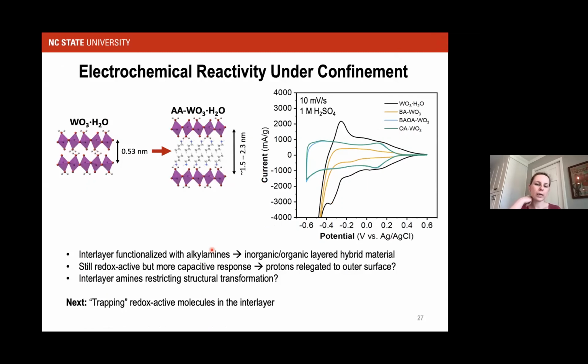And the way we're doing it is through layered materials, of course, our favorite. We're looking at things like tungsten oxide hydrates, which we also study a lot in our group. We're using some really interesting reactions to get organic molecules into the interlayer and prop open this interlayer to be about 2 nanometers. And we see very interesting electrochemical response. You would think with these greasy alkylamines, maybe your material would no longer be redox active in an acidic electrolyte, but we actually find that the electrochemistry is very, very reversible.